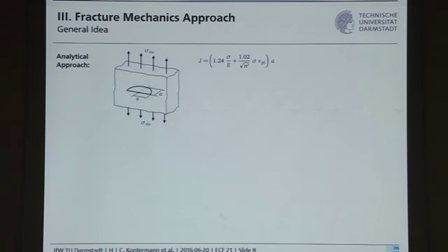But maybe we can learn from these analytical solutions. So the issue is now to determine an appropriate delta J value, so cyclically elastic plastic J integral, which is controversial, discussed in the literature, but maybe Dowling suggested to put analytical equations for J, and not only work with absolute values of stresses and strains, but with stress ranges and strain ranges, in order to get not only J, but delta J. So this is very simple, but the idea maybe is transferable also to FEM.